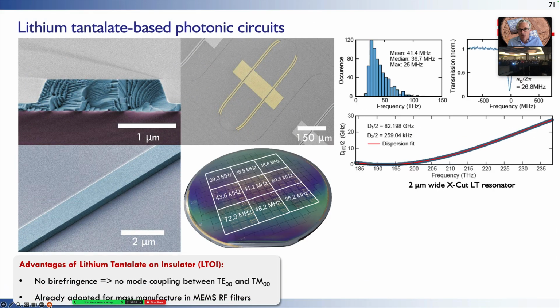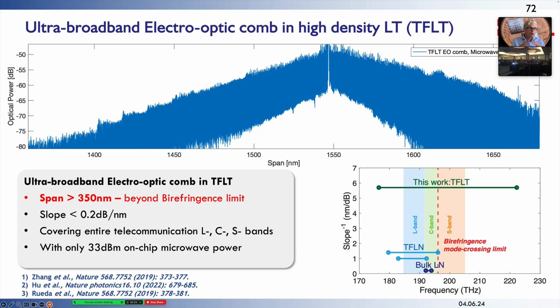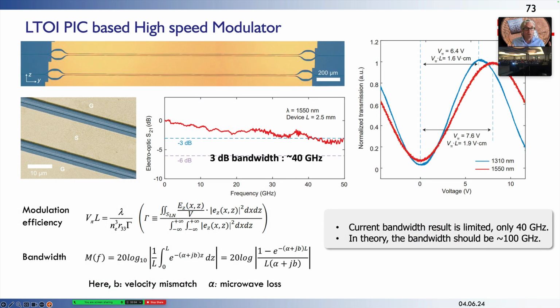We just flash through one example here. We can generate ultra broadband optical frequency combs, electro-optic frequency combs that span several thousands of lines, which could be used, for instance, for microwave to optical conversion experiments, or actually for low-noise microwave generation using two-point frequency division. And another example, what we can generate is actually very high-speed optical modulators that can run with frequencies up to 100 gigahertz and have driving voltages on the level of just a few volts. And this is possible by using these materials like lithium niobate, lithium tantalate, combined actually with these low-loss etching techniques.